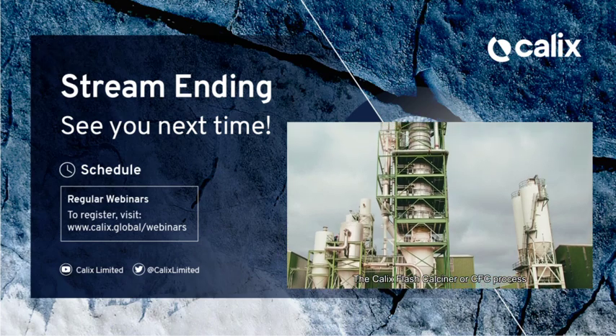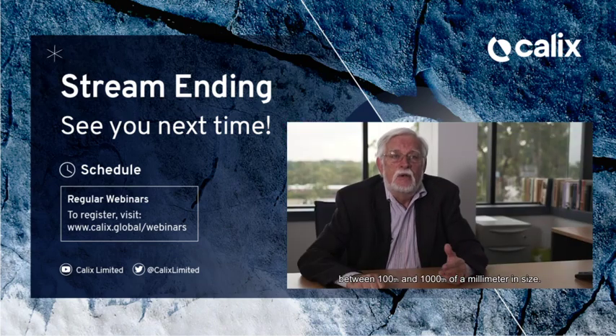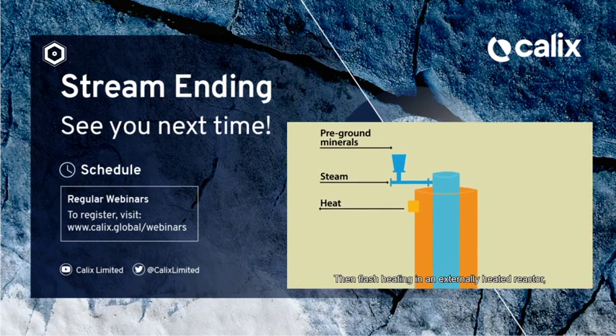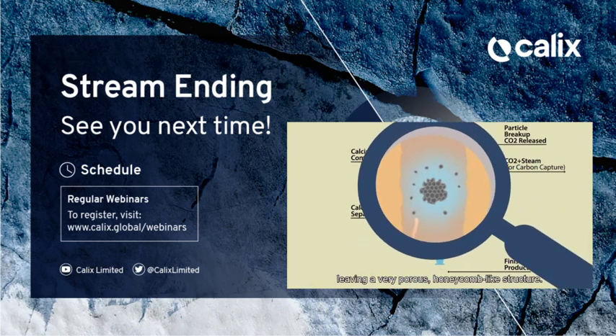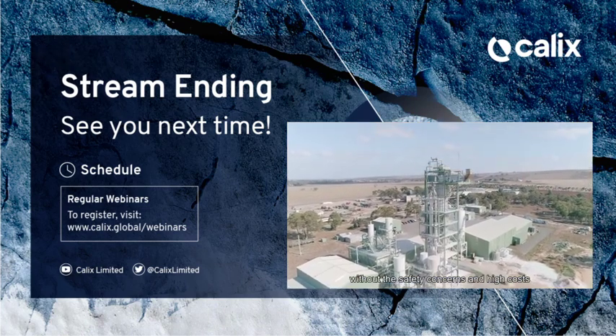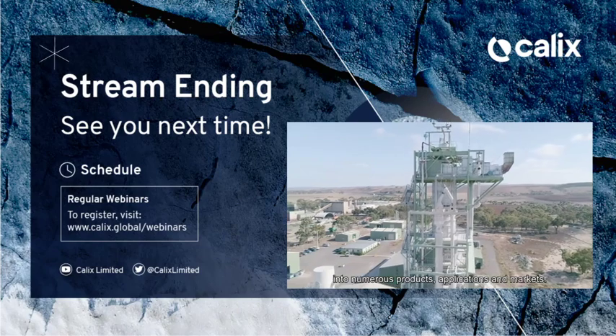The Calix flash calciner, or CFC process, involves grinding minerals or other feedstocks to between 1/100th and 1/1000th of a millimetre in size, then flash heating them in an externally heated reactor in a very short time, up to about 950 degrees centigrade. As trapped gases in the material bubble out through the particles, they create highly porous structures. These particles are then cooled very quickly, leaving a very porous, honeycomb-like structure. New materials produced by the CFC are proven to have similar reactive properties to nanoparticles, without the safety concerns and high costs, but with all the benefits that nanotechnology is developing into numerous products, applications and markets.